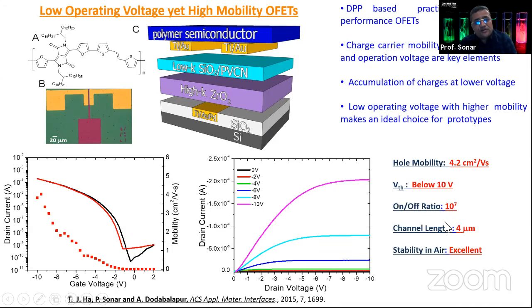Again, if you want to use this in a microprocessor or some type of circuit where industry wants to put them in a flexible prototype, they want this bottom contact. And for that, channel length is very crucial. Channel length is the length between the source and drain, the two electrodes. If you have a shorter channel length, the more devices you can put in a circuit, and then we can have a higher speed. So this is a 4 micron channel. Most of my earlier slides showed 50 micron channel length devices, but this was the lowest one. And there are some limitations in making very small channel length devices because of lithography and some nanofabrication limitations.